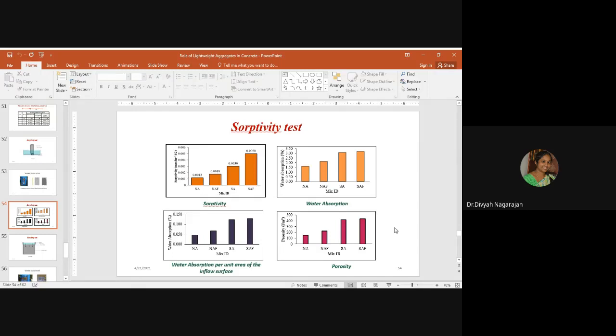Water absorption. The water absorption of the concrete mix was calculated during the 24 hours of observation. The sintered fly ash aggregates showed 16% higher water absorption, but as a matrix inside the concrete, the rate of water absorption is considerably low. That is, when sintered fly ash aggregates alone were tested in the laboratory, they had 16% water absorption. But since saturated and surface dry aggregates are used in the concrete, it had a better impact on the concrete.